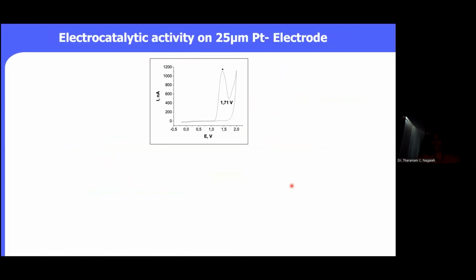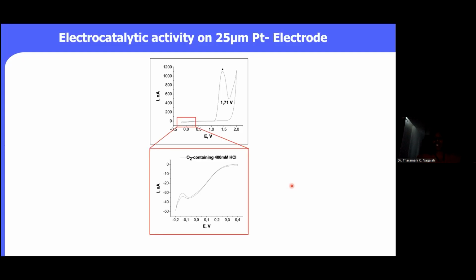Here, I'm not going to introduce the macroelectrochemistry. I just want to give a brief introduction about microelectrochemistry and how one can utilize the scanning probe technique to establish or design a stable catalyst for a particular system. So what we have done is that we have taken the platinum microelectrode and performed normal cyclic voltammetry. And you can see that there is an increase in the oxidation current. Again, we are speculating this is due to the chlorine oxidation. And on the cathode, we see that this is due to the oxygen reduction reaction.